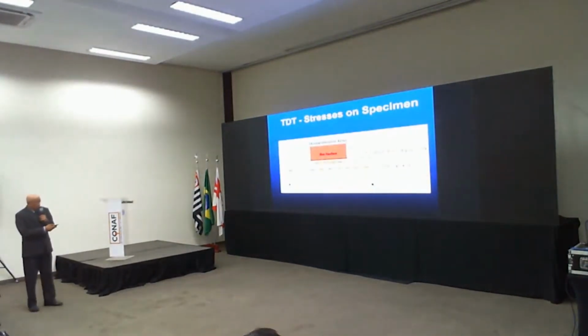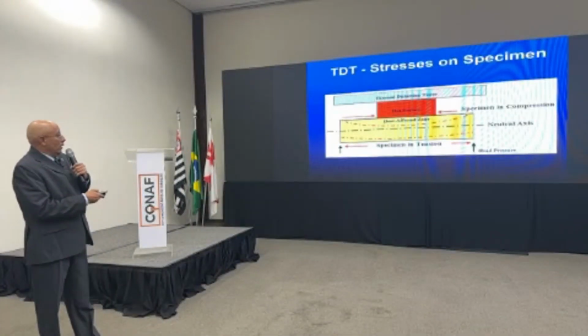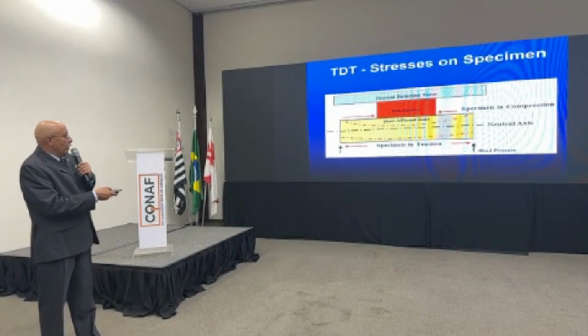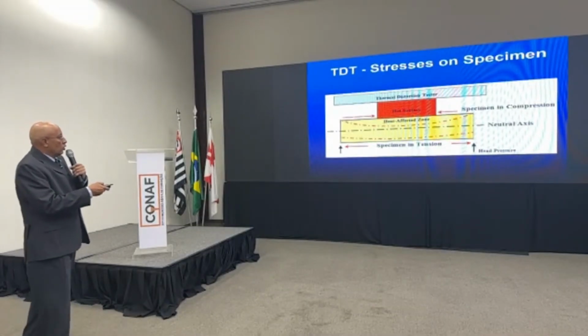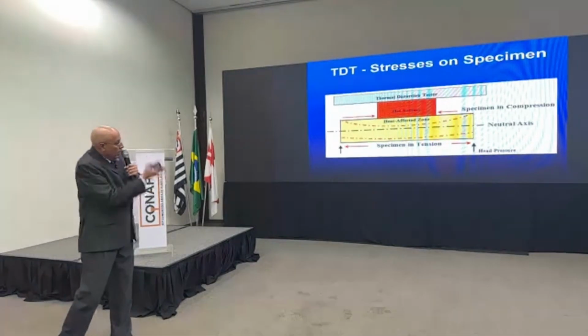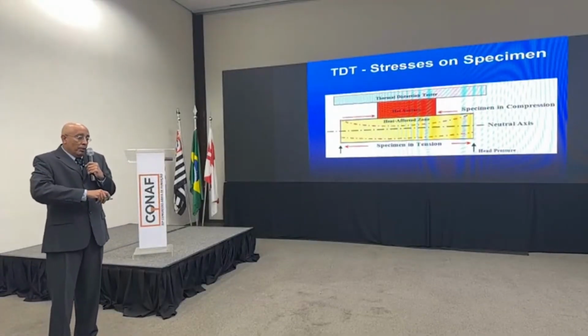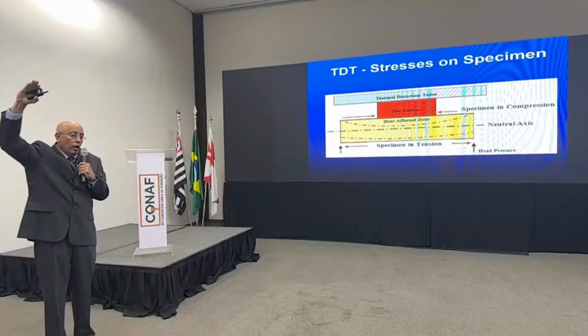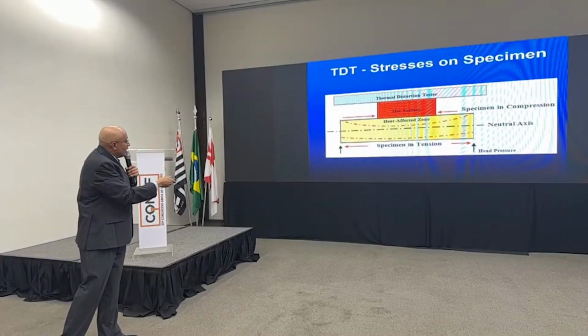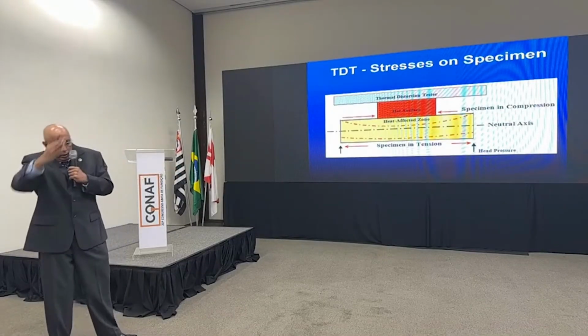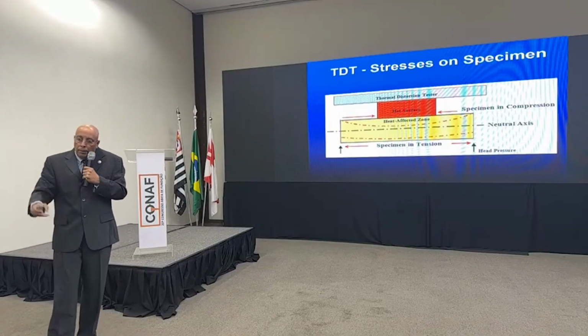To show you this in a cross-sectional view, the neutral axis is not what is important, it's the rotational axis of where the cookie hot surface interface is, which would represent the mold metal interface in casting, and we're delivering the head pressure against that. So if the cookie is moving away from the hot surface, that would represent pure expansion, a curve moving up. If the cookie sags around the hot surface, it would result in plastic deformation, up and then downward movement.